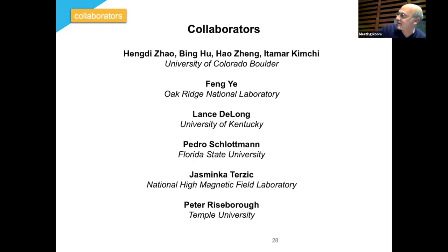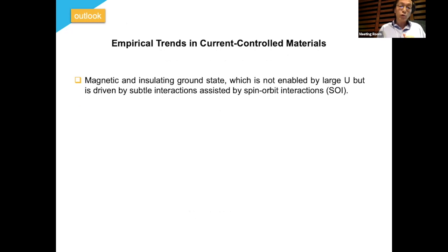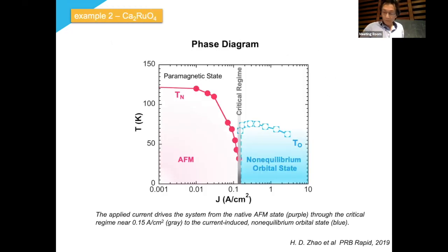My question is, the current densities are quite substantial. So I wonder if there are hysteresis effects and if you characterized them. Yes, there is. You're saying the hysteresis effect, right? Yes, there is a very strong hysteresis effect when the current is beyond this, for instance for this calcium-2 system. In this region, the hysteresis is very, very strong. It's so strong that the relaxation time could be a few days. So we really don't understand what's going on there. But below this, the hysteresis behavior is very weak.